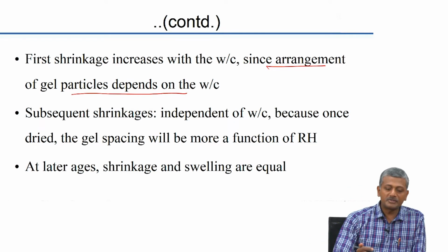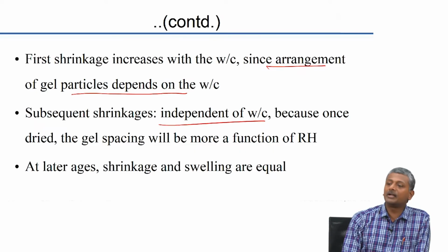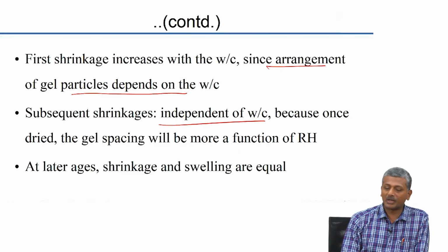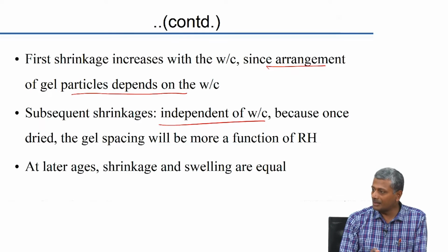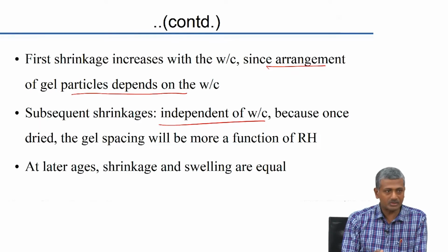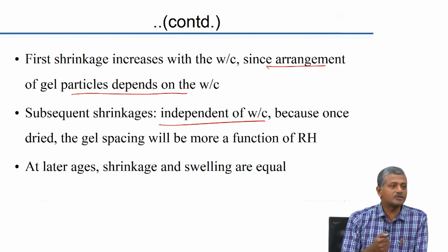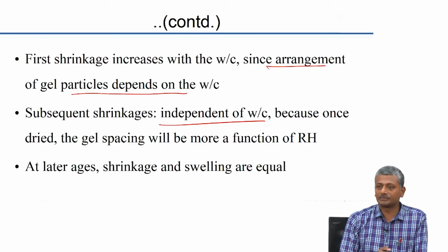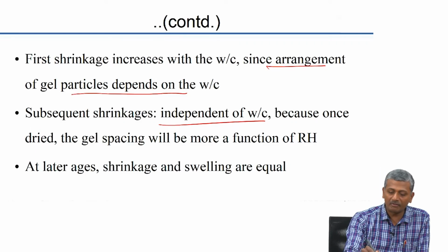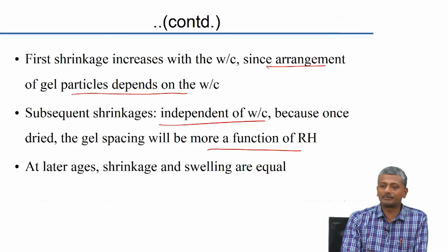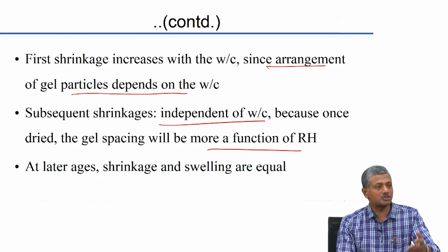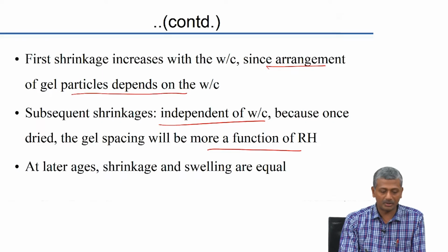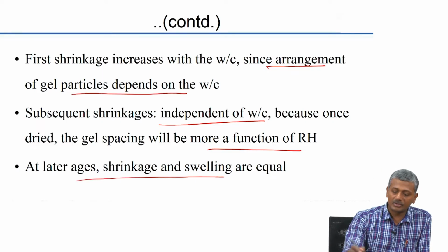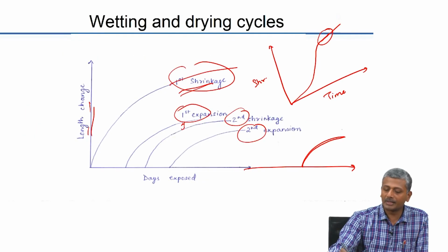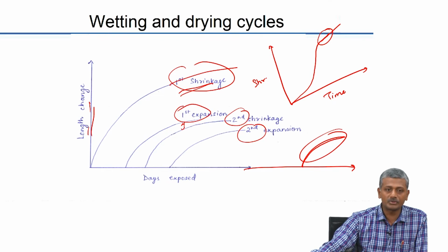Okay. Subsequent shrinkages become independent of water cement ratio, because once you dry the gel and alter the gel structure, there is only so much you can do to the same structure. It is only going to be a function of the relative humidity in the environment. Subsequent shrinkages will only be a function of the relative humidity. At later ages, once you come to the long term, the extent of shrinkage and swelling will become almost equal.